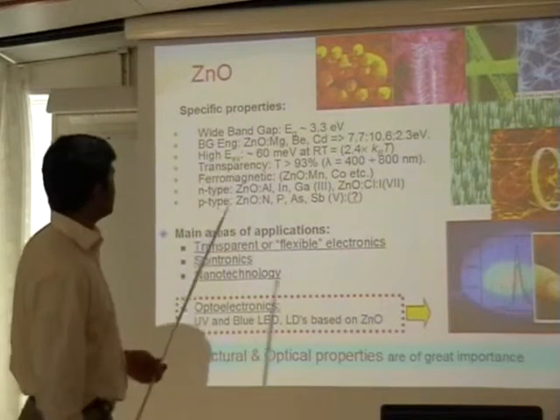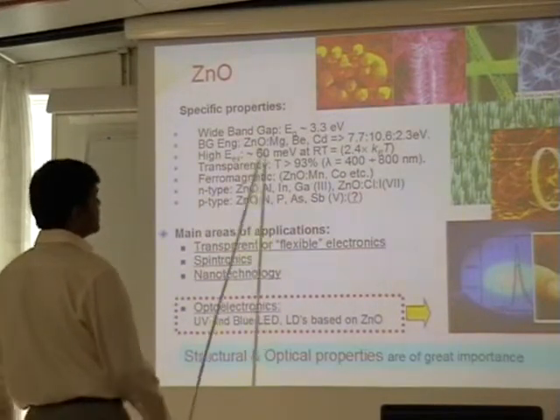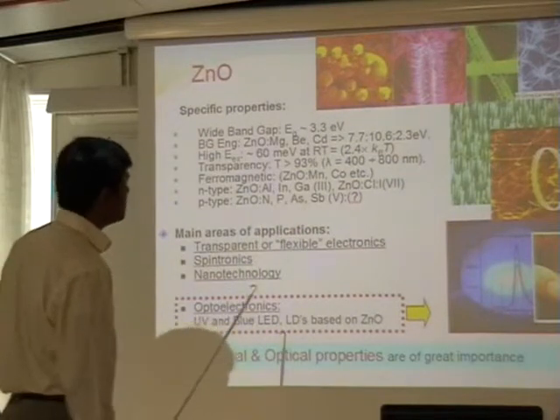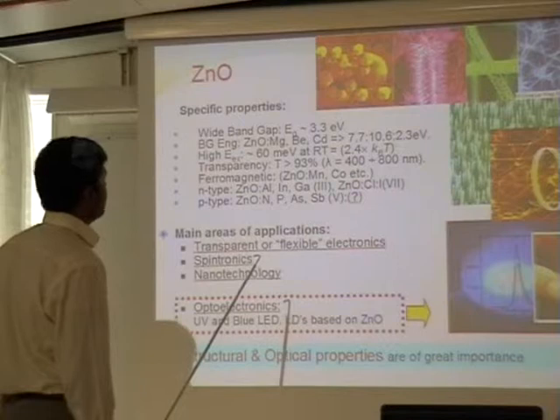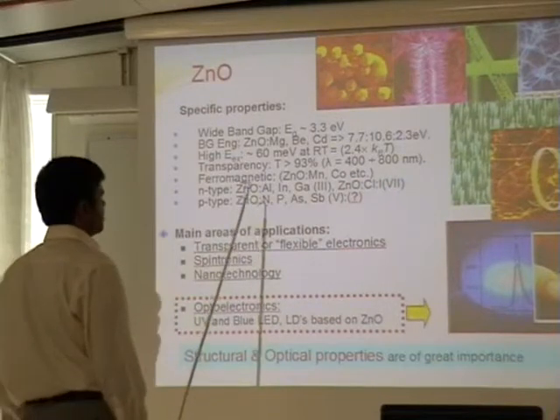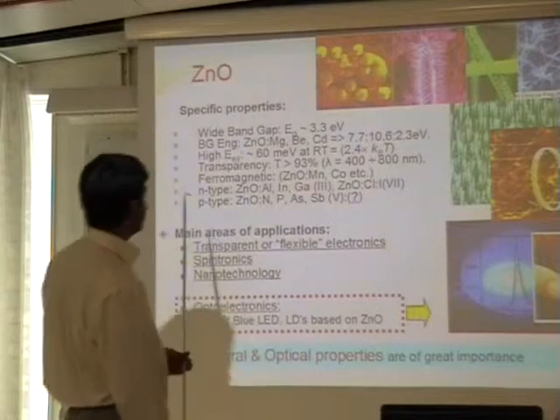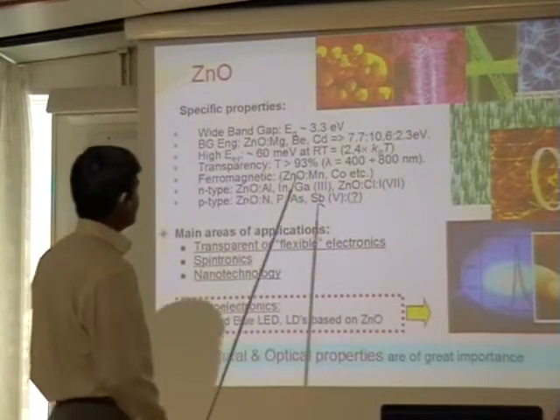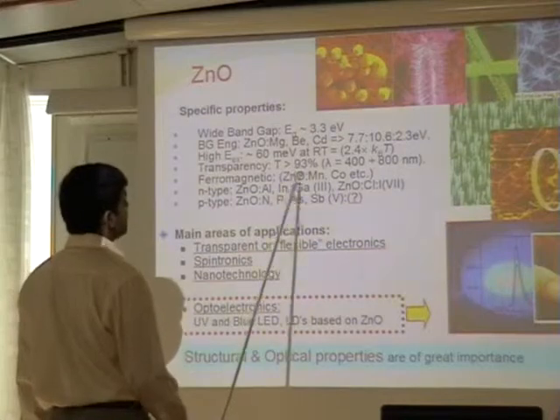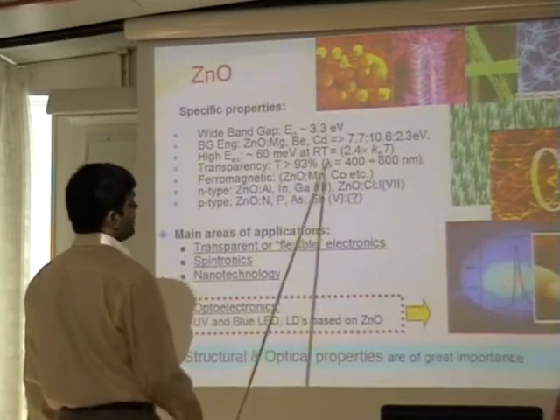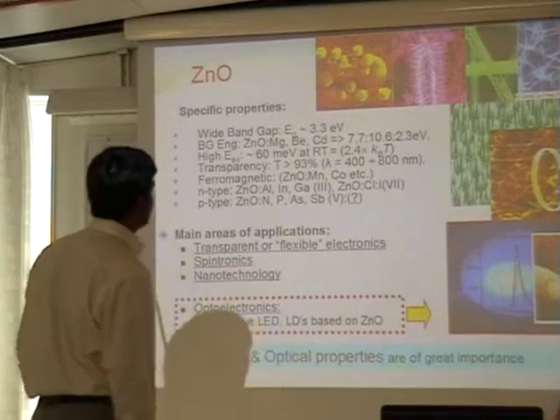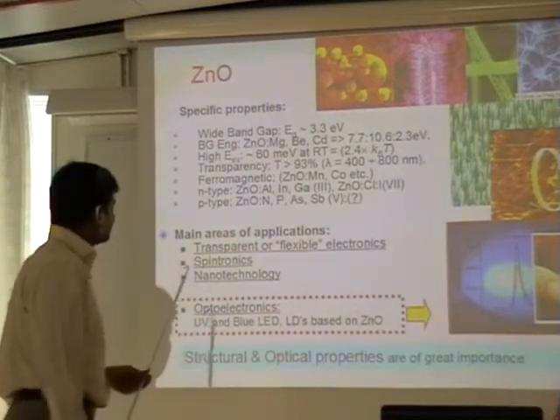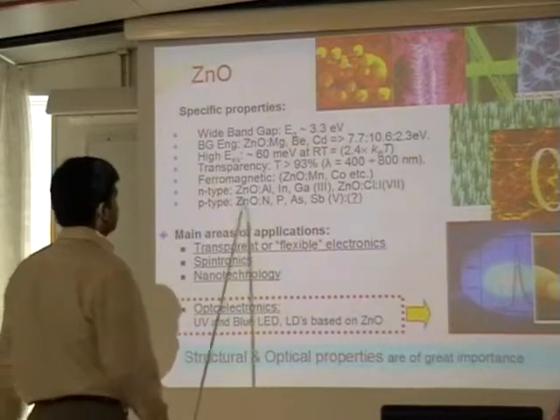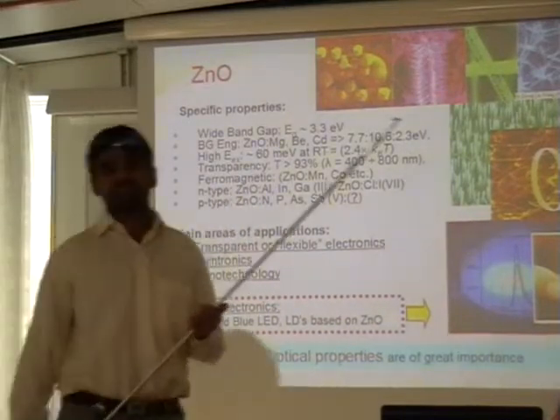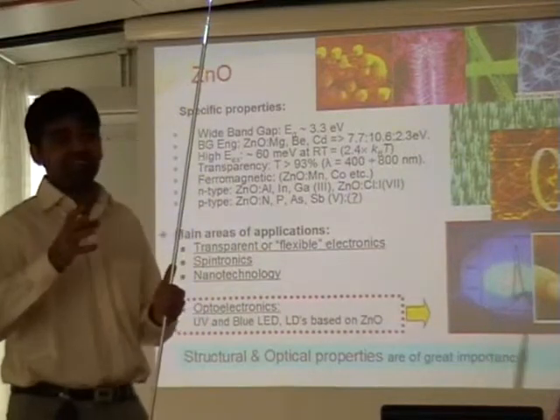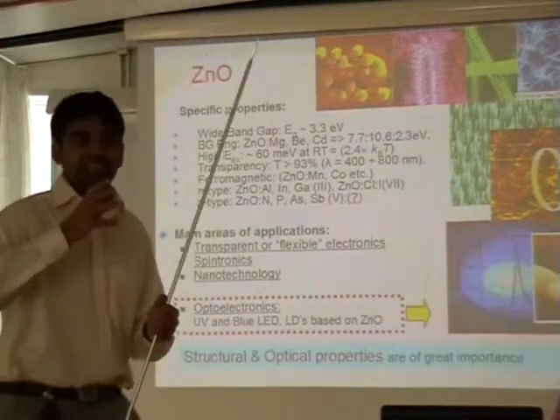They have a high exciton binding energy, near about 60 milli-electron volt at room temperature, and the bi-exciton value is 15 milli-electron volt. Zinc oxide is a transparent material. Its transparency is greater than 93%, and the wavelength range is 400 to 800 nanometers. Zinc oxide exhibits ferromagnetic properties. These are diluted magnetic semiconductors.